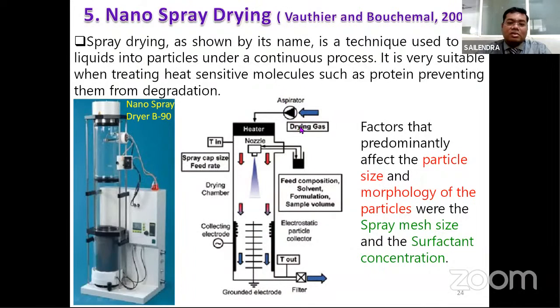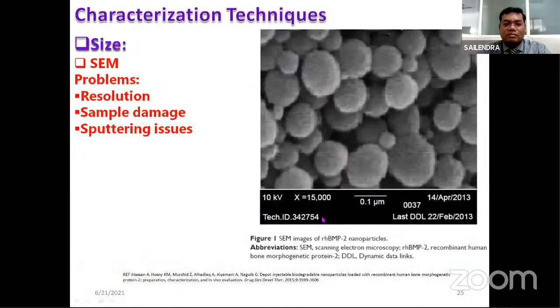Now, the good thing about this one is you can control the particle size based on the spray mesh size. You have a very small spray mesh size at the nozzle. You just reduce the size of the mesh, you will get less particle size. You increase the size of the mesh, you get large particle size. And surfactant concentration. You will also have a surfactant that lubricates the movement of the particles within this chamber. So surfactant concentration is also very, very important in industrial scale preparation of nanoparticles.